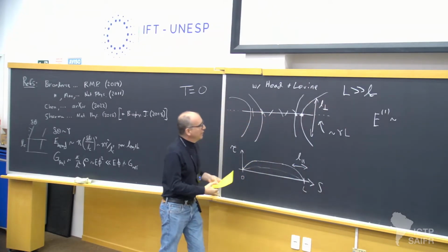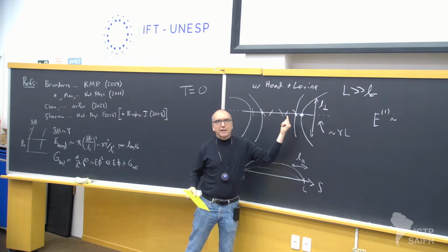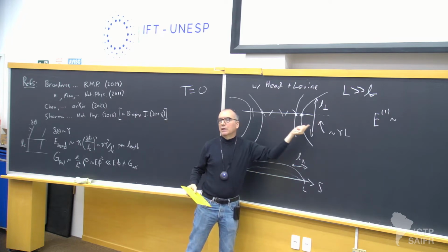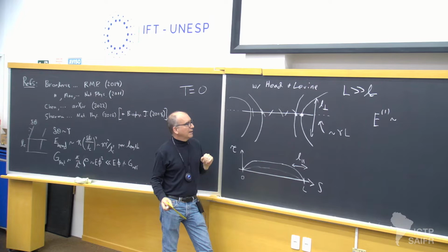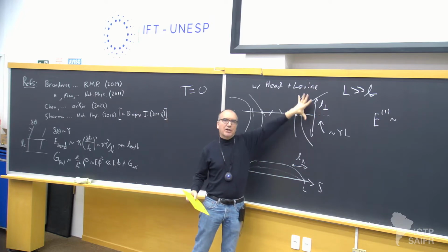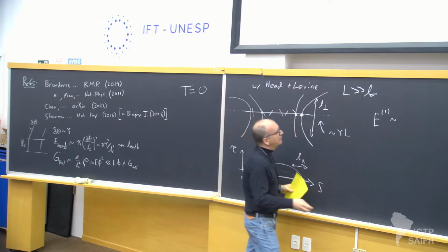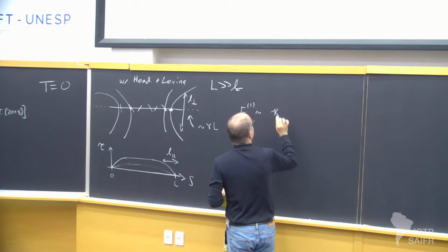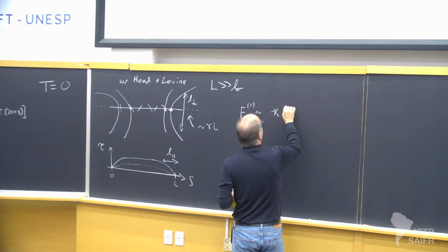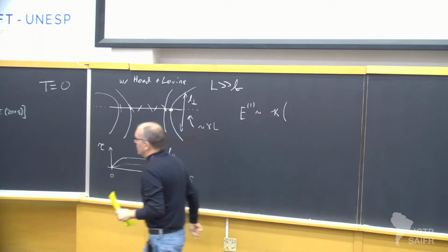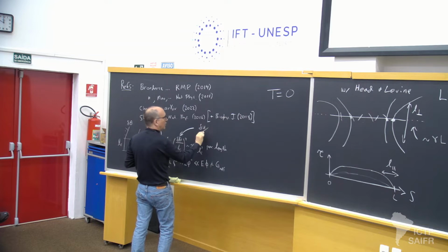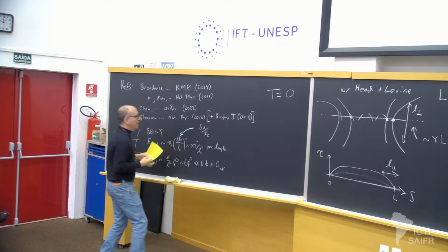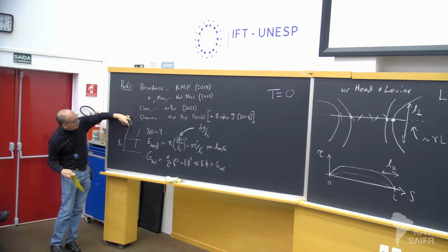Call it L perp. So again, the idea is L parallel is going to characterize something about the longitudinal range over tension propagation, you could say, in the fiber. L perp is going to characterize the range of the bending away from the fiber among the other fibers. And so I could estimate the energy here as follows. I could say, well, the degree of my deformation here, so this delta theta that appears here, is also a delta U over LC. Delta U being this displacement, right?